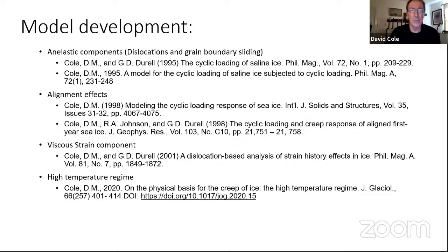But this is mostly, for the record, the development of the initial dislocation-based anelasticity model. That was back in the 90s. We then expanded it, once we started doing field work and getting into aligned ice, we brought in alignment effects, and developed a more sophisticated viscous straining component about 20 years ago. And then as one of my retirement projects, I've been revisiting some of our results and realized that I could, in fact, extend the model virtually up to the melting point for freshwater ice.